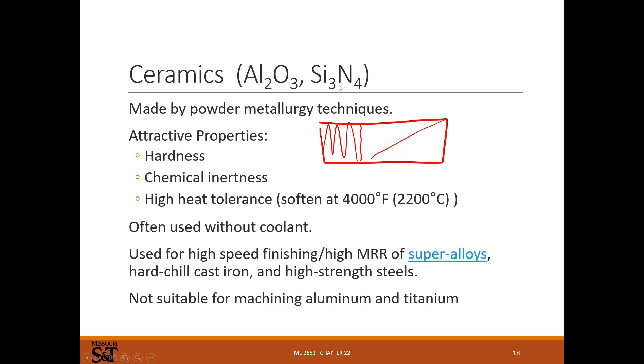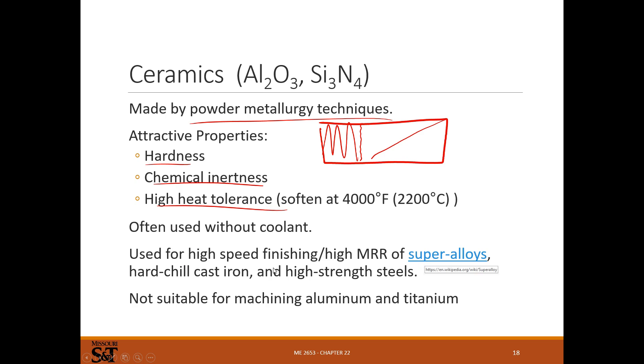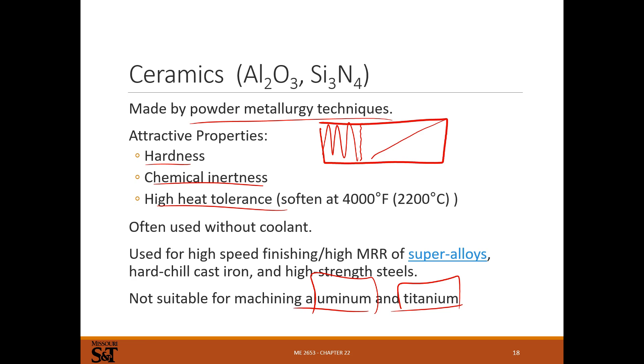Ceramic tooling — things like aluminum oxide or silicon nitride — it's harder to make these into actual tool shapes. They're still made by powder metallurgy. Ceramics are hard, which means they'll be strong and chemically inert, with higher heat tolerance. But they're more brittle, which means less tough and more likely to break. They're not used for aggressive operations — mainly for gently machining very hard things like nickel-based super alloys or some really high-strength steels. They're not suitable for aluminum or titanium. Aluminum is pretty easy to machine, so you really don't need anything too fancy for it.